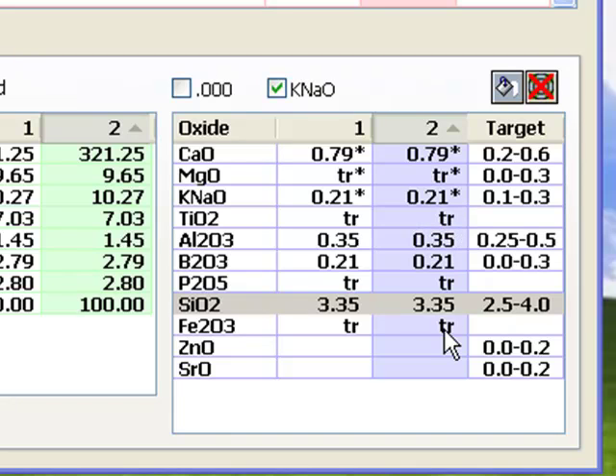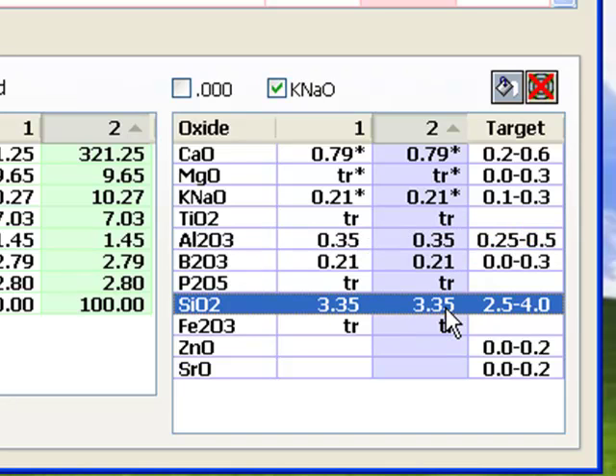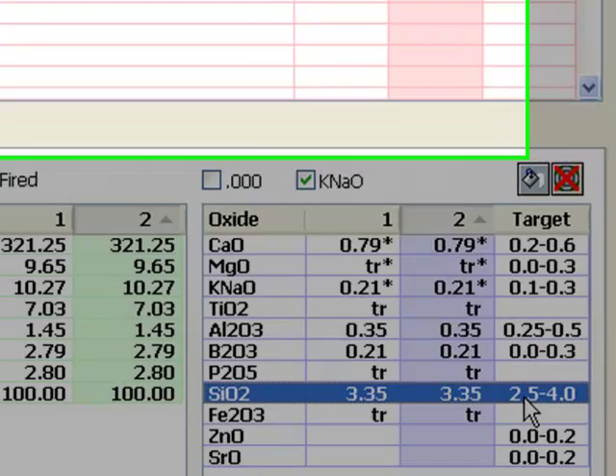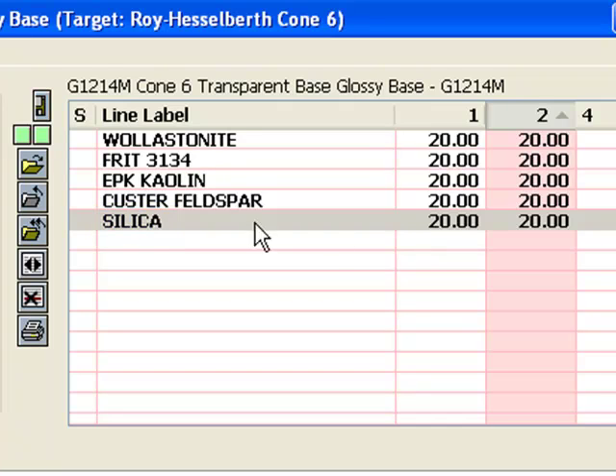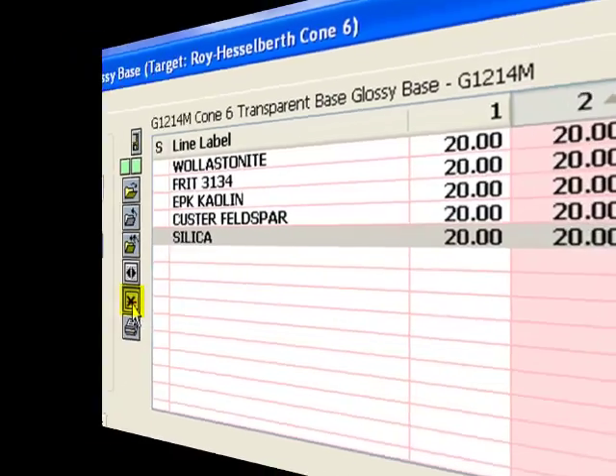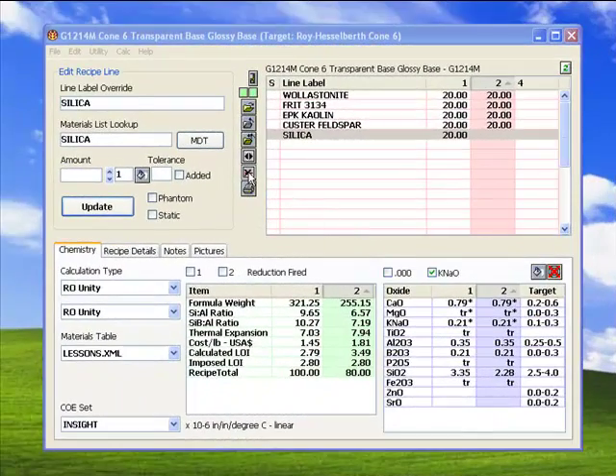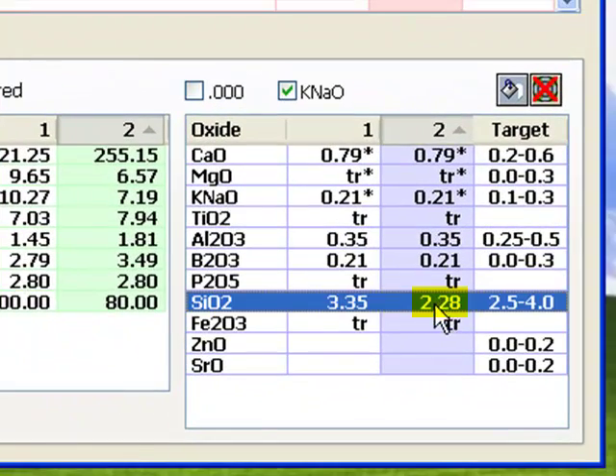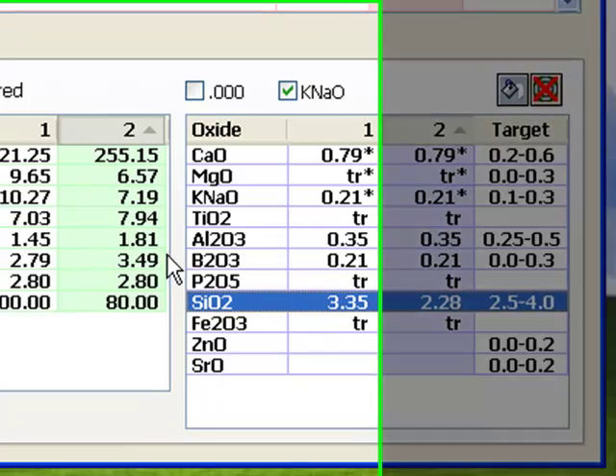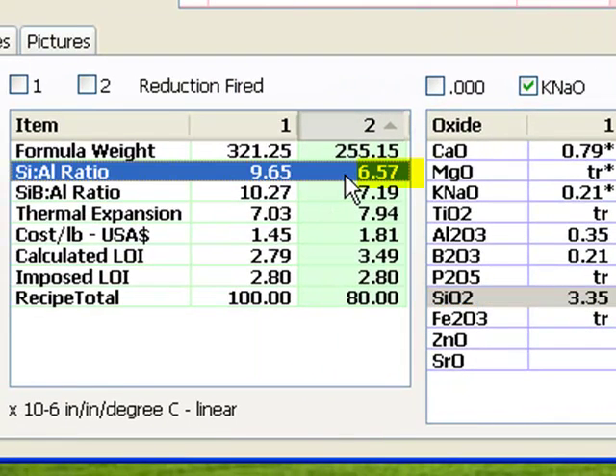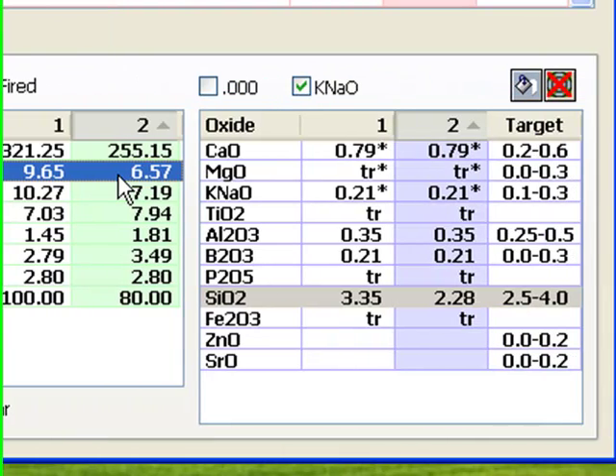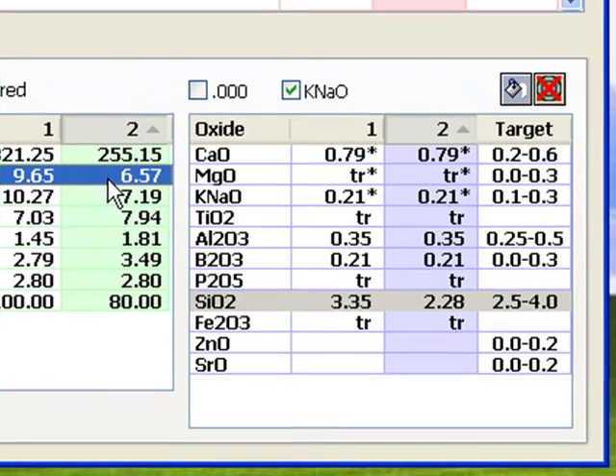Now we are going to increase the Al2O3 to the upper end of its range and reduce the SiO2 to the lower end of its range. The first obvious step is to remove the silica in Recipe 2 to reduce SiO2 in the formula as much as possible. I can do that by editing the line to 0 or clicking this button. Notice how much the SiO2 has dropped and how much lower the silica-alumina ratio is. Again, this ratio is an indicator of gloss in alumina matte glazes, and it needs to be around 5 to 1 for this type of glaze to be a good matte. Thus, I need to bring it down more.